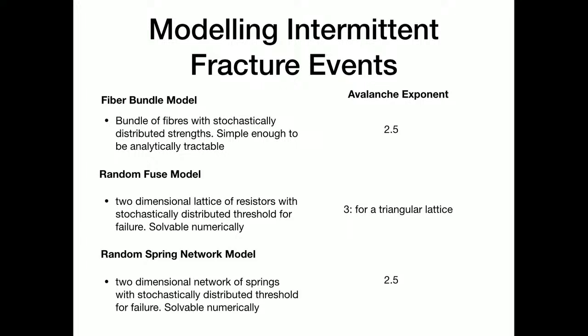So all these different contexts talk about what is the power law and the power law behavior. And in modeling, there are several models which are popular in this context of generating the avalanche statistics and the power law behavior. And they have successfully shown that there is existence of power law behavior in breakage of fibers in the fiber bundle model, in the burnout of resistors in the random fuse model, and of course breakage of springs in the random spring network model. And these models have, apart from reproducing this avalanche statistics or power law behavior, also provided a lot of insights into various other aspects.